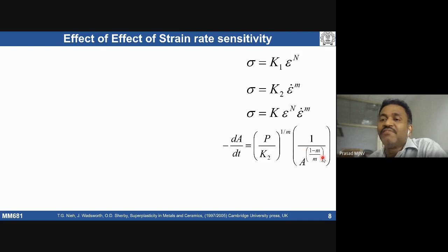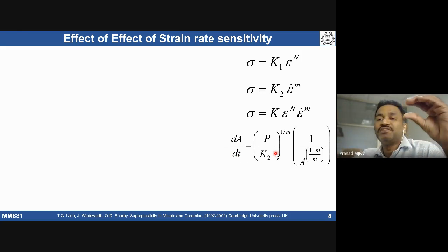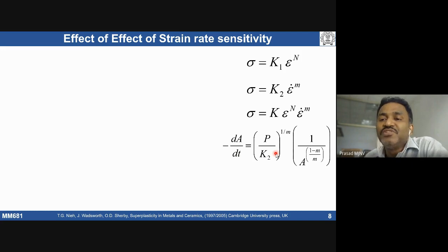So the higher the m value, the rate of area change, that means the reduction, the cross-sectional area changing with time, is going to be constant. That means there is no necking if m is equal to 1. So the higher the m value, we can get a uniform elongation. The rate of uniform elongation is going to increase with increasing m value.